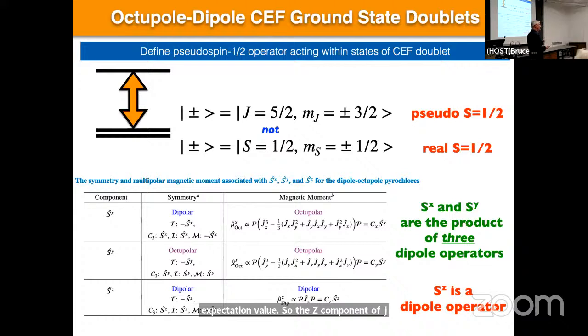But the X and Y components of J will not. And the reason they don't is because the two states that make up the ground state doublet are Mj equals, say, minus 3/2 and plus 3/2. And to get from minus 3/2 to plus 3/2, it doesn't take one raising operator, it takes three raising operators. So if one raising operator has a dipole character, then three actually has an octupole character. Two would have a quadrupole character. Okay? So the net result of all this is that for our pseudo spin a half degree of freedom, there's a dipolar moment associated with the Z component of spin, but there are octupolar moments associated with the X and Y components of spin.